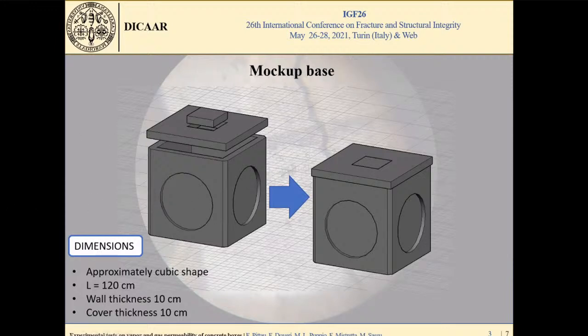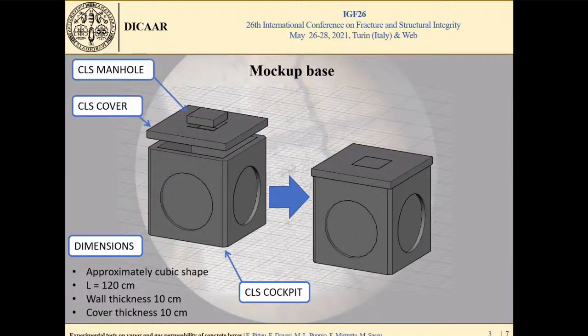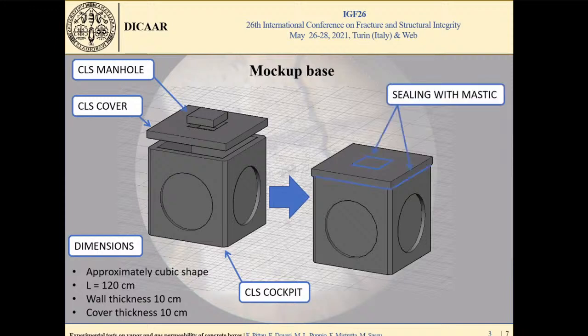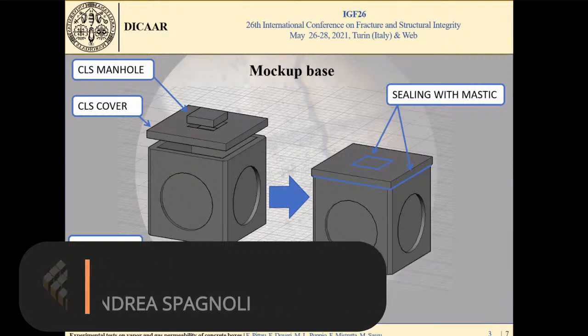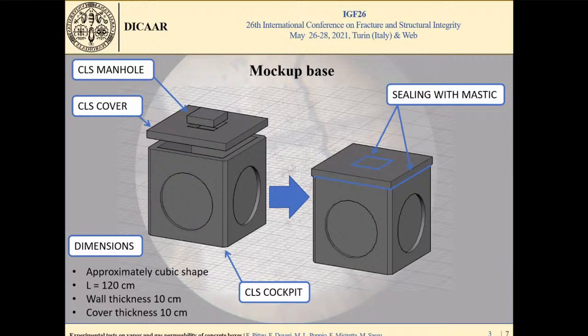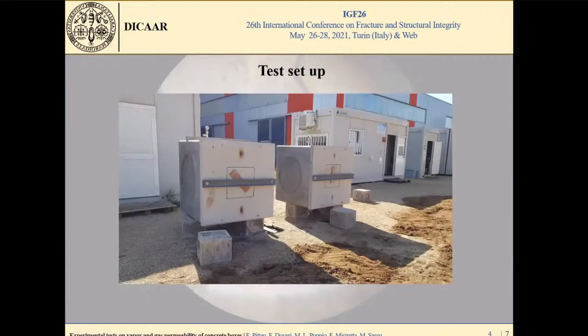So in the mockup, we have the concrete cockpit, the concrete cover, and the manhole, usually used to inspect the cockpit. We sealed all the joints with mastic, as in this picture. The main characteristic that I want to highlight is the wall thickness of the boxes, which is very reduced, only 10 centimeters. In this picture, you can see the first step of the test setup, the preparation of the mockup.